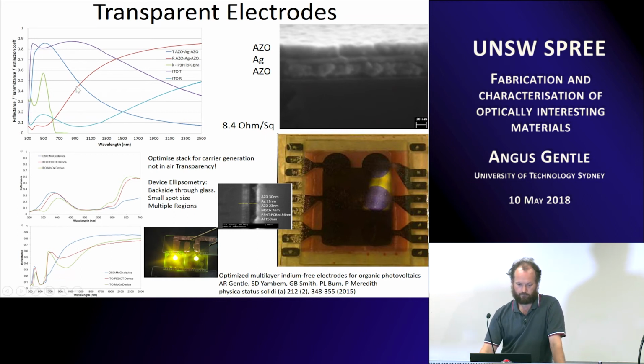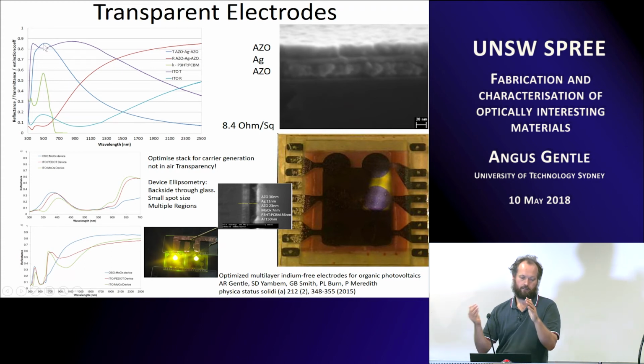And so with this one, doing this AZO, silver AZO, you can see it's slightly more transparent than an ITO glass slide at the relevant wavelength for the design we're doing. So this one here was designed for transparency in air, which is usually when people do metrics of transparent electrodes, they say, what's the transparency in air and what's the sheet resistance?